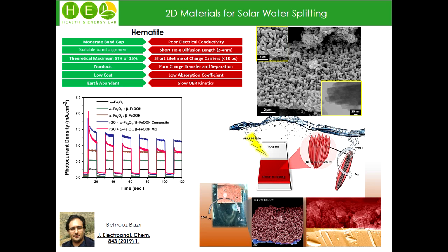But at the same time, it suffers from some disadvantages, like poor electrical conductivity and short hole diffusion length, which limits the oxidation reaction on the surface, and also sluggish oxygen evolution kinetics on the electrodes, and poor charge transfer and separation in such material.